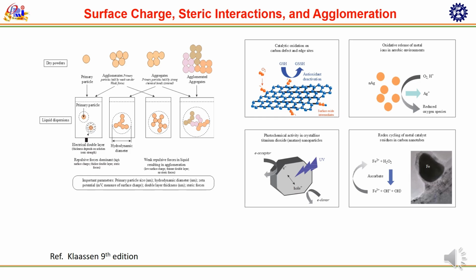Here we can also show the surface charges, steric interaction and agglomeration. Primary particles are individual nanoparticles. You can see here the nanoparticle. In dry powder, the primary particles can agglomerate, aggregate, or form agglomerated aggregates. Agglomerates are loosely bound by weak van der Waals forces, aggregates are strongly bound by chemical bonds, and agglomerated aggregates are a mixed state with both. In liquid dispersion, nanoparticles interact with water and ions, forming an electric double layer around each particle.